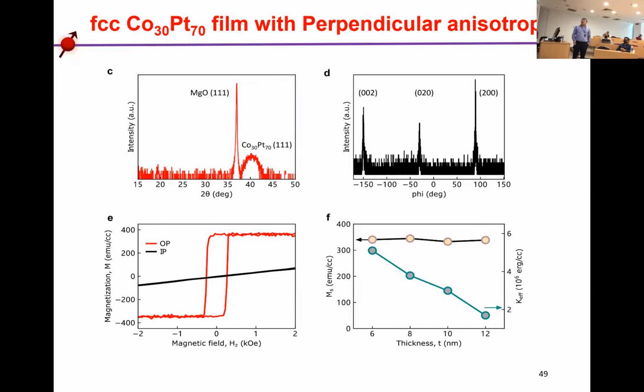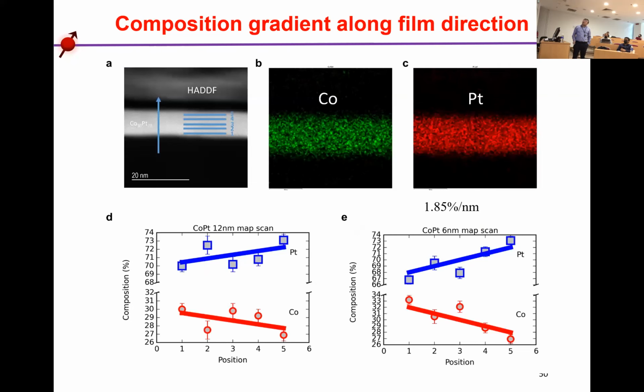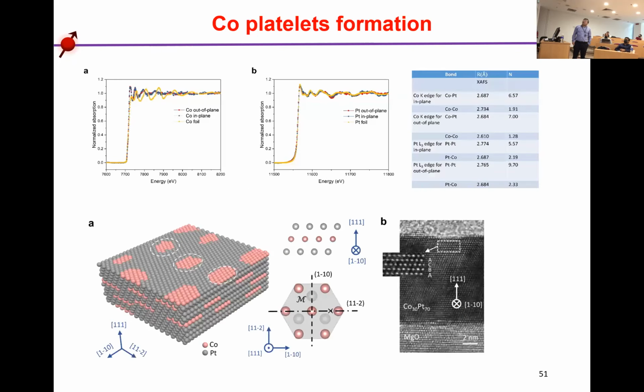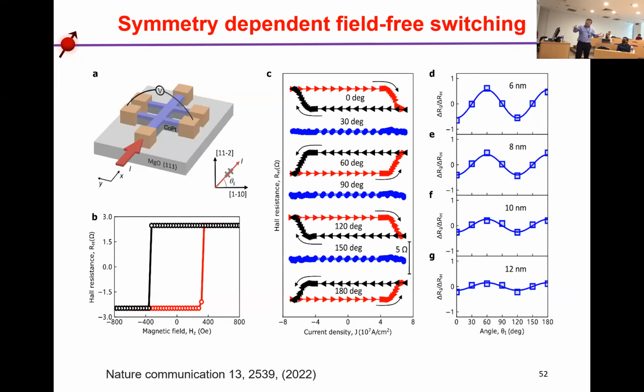So from here we can also see some composition gradient, and then we use the results to evaluate the anisotropy of the cobalt platelets, because when the bonding in the lateral direction is larger than in the vertical direction, that means they form cobalt platelets. We have demonstrated this using examples, and definitely the single ferromagnetic layers we can switch. We call it self-switching. We did not apply any field, just electric current. We can self-switch these magnetic materials. From here, it's a threefold symmetry.